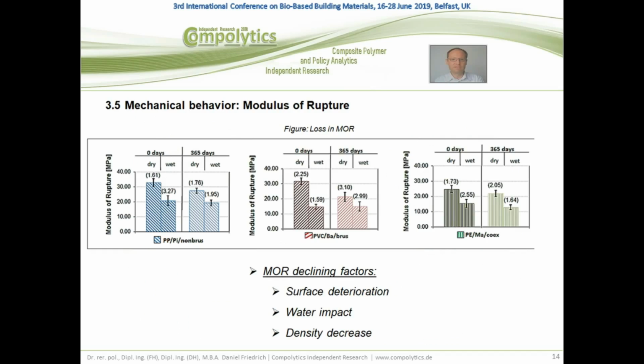The modulus of rupture also went down. There were nearly no differences between the three samples, so all three WPC types significantly reduced their modulus of rupture after 1 year. This is also due to surface deterioration by fiber detachment and also polymer chain scission by the UV radiation, but also by water impacts which stayed in the compound, and also the decrease in density led to a significant loss in MOR.